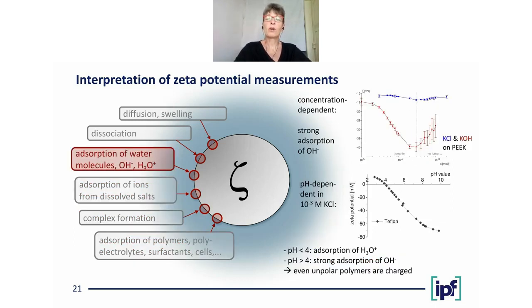Another thing that is important to know if we have a look at Zeta potential measurements is the extremely strong adsorption of hydroxide ions on all surfaces. In the top graph, you see a comparison of concentration-dependent measurements in potassium chloride and potassium hydroxide, and you see how increase of the hydroxide concentration increases the amount of the negative Zeta potential, while the chloride ions don't have a big effect.